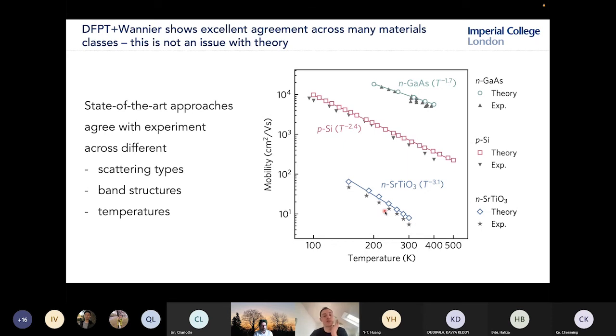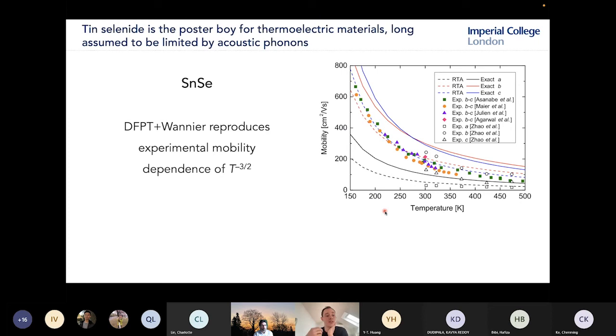Now, when these methods started being applied to thermoelectric materials, there were some unusual observations. Tin selenide has long been considered dominated by acoustic phonons, and that's because its mobility shows this T⁻³ᐟ² temperature dependence, and that's what I'm showing in this plot here. I think the experiments are these filled circles, these filled shapes.